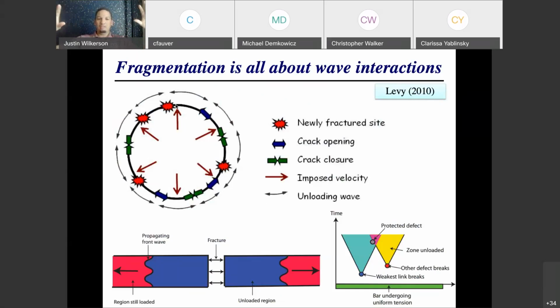And so every material point just knows that it needs to be stretching and expanding out radially at some constant rate. And then all of a sudden, some point far to the right of you fails. Well, you don't know that that point failed until an elastic release wave propagates over to you and tells you that it failed. And so when that wave comes to you and tells you that it failed, then you will change your loading condition. But until that happens, you will not change your loading condition. So you will continue at that same strain rate until you get that information.